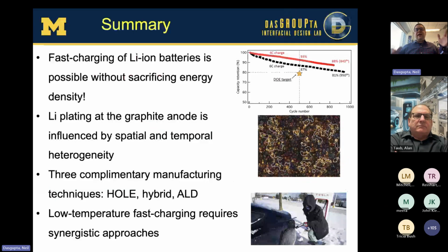So in summary, I showed you fast charging is possible without sacrificing energy density, that lithium plating is really this key bottleneck, and that's influenced by this spatial and temporal heterogeneity. I showed 3 complementary manufacturing techniques, and I showed if you start to combine multiple of these approaches, you could start to do truly remarkable things like 6C fast charging at low temperature without lithium plating.